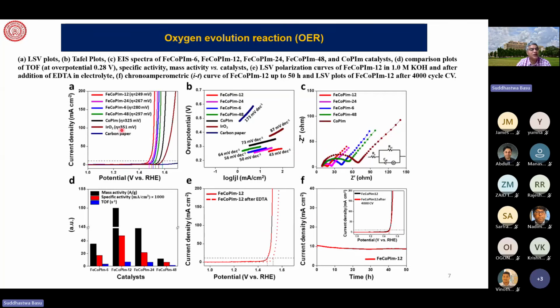And you compare our results with a carbon paper, cobalt phosphonate, iron cobalt phosphonate, different reflux time. And you can see that 12 hours of reflux time, the red color, had the lowest onset. Okay, so lowest onset potential. If you plot the Tafel slope, if you see here,